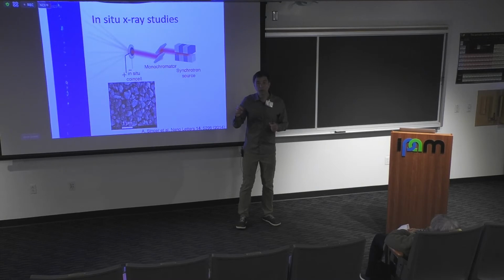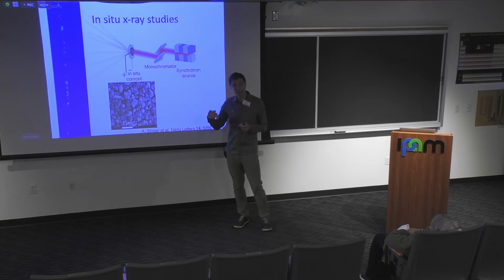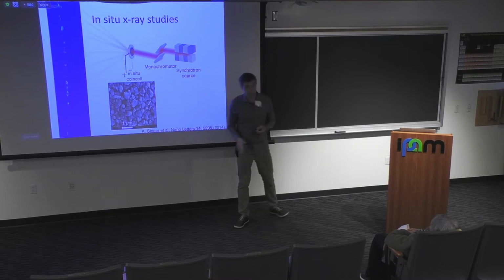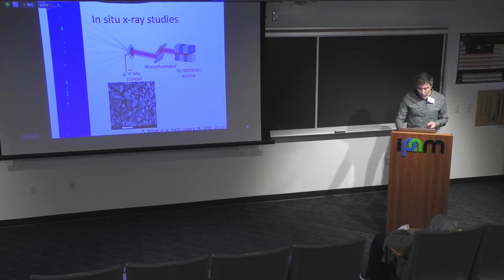But the interesting thing is that by following multiple particles, we can understand that not all of them go through this process at exactly the same time, even though they're in equilibrium with each other, which tells you already that the presence of defects or size differences are important in the system, right? It's not happening uniformly, so to speak.